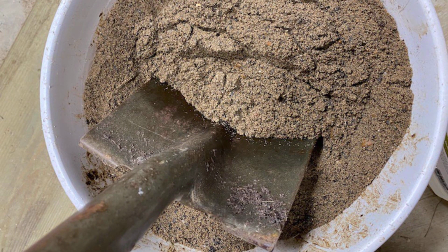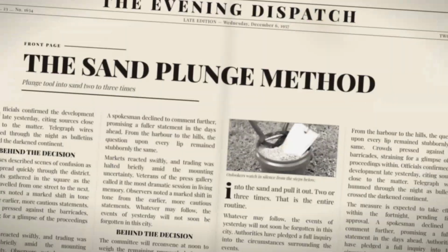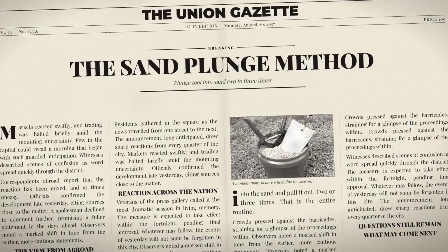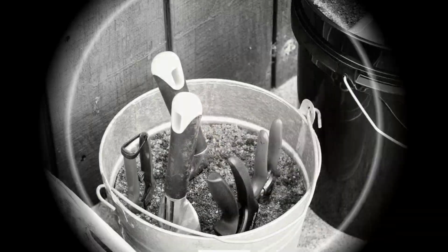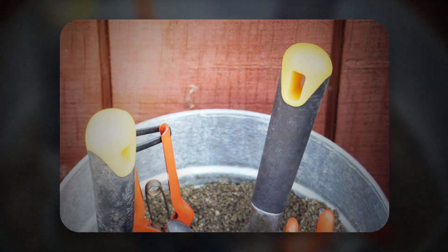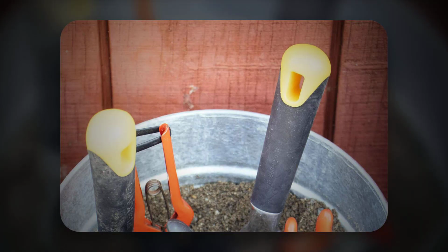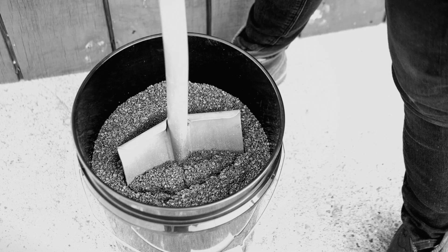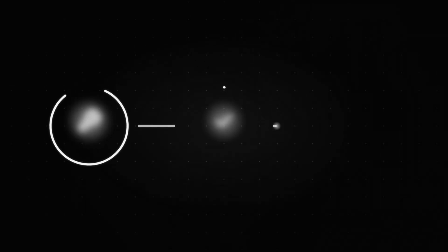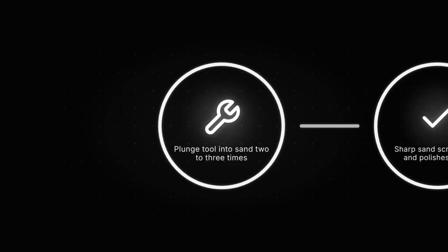When you come in from the garden, plunge the shovel, the trowel, the fork, or the hose straight down into the sand and pull it out 2 or 3 times. That is the entire routine. It does 3 separate jobs in one motion. The sharp sand scrapes the soil off the blade, which matters more than it sounds, because garden soil holds moisture against steel for days, and any fertilizer residue in it is salt-based and highly corrosive. The abrasion is mild enough that it polishes rather than scratches. And every grain carries oil, so the tool comes out with a thin, even film already applied across every surface, including the ones you would never bother to wipe.